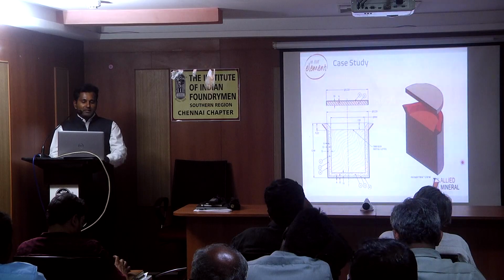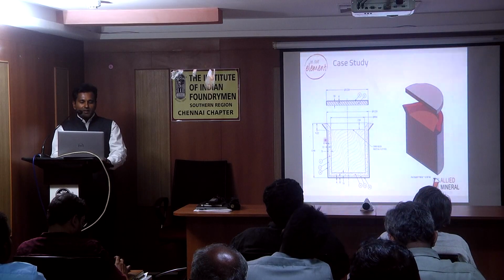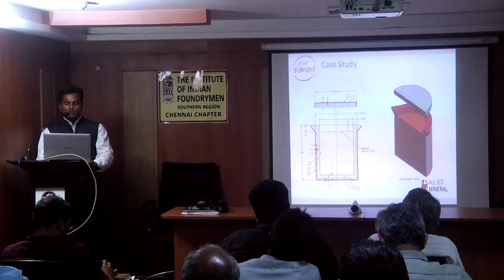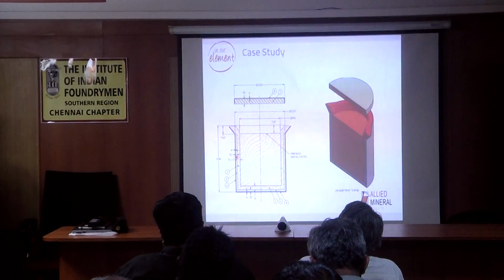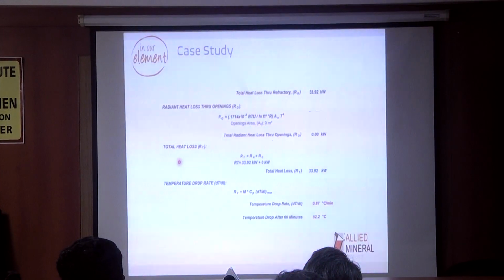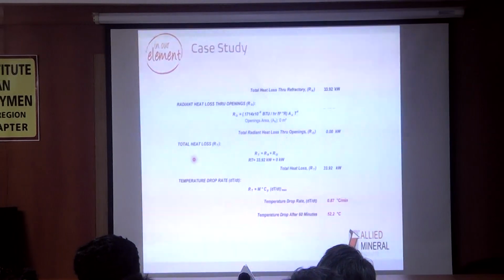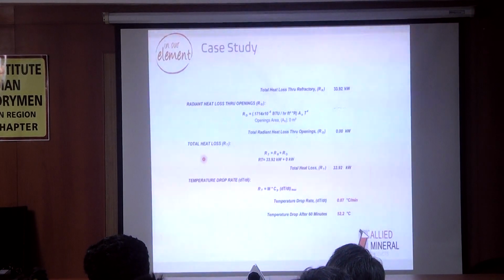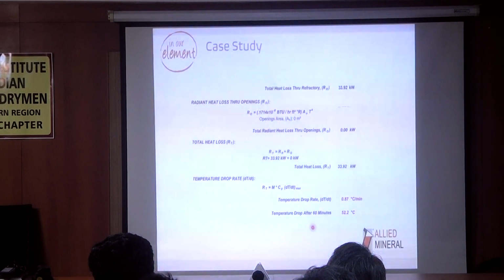This is the design we have given: 6 mm ceramic fiber paper and 32 mm insulation fabric, then 75 mm of castable lining with a 100 mm cover. This is the heat loss we have given theoretically: after 60 minutes, a temperature drop of 52.2 degrees.